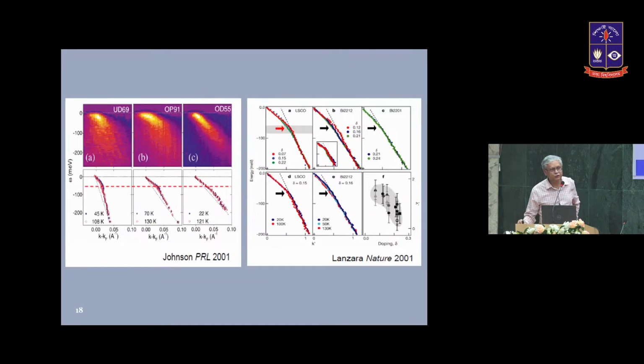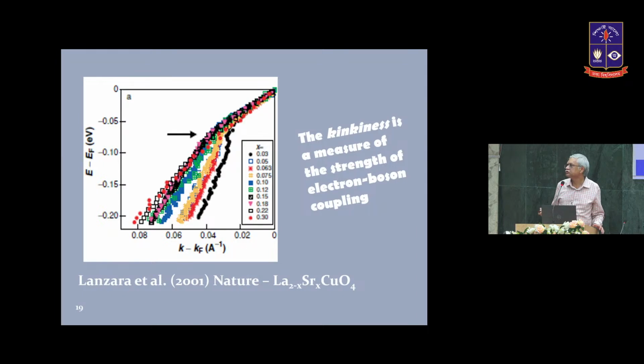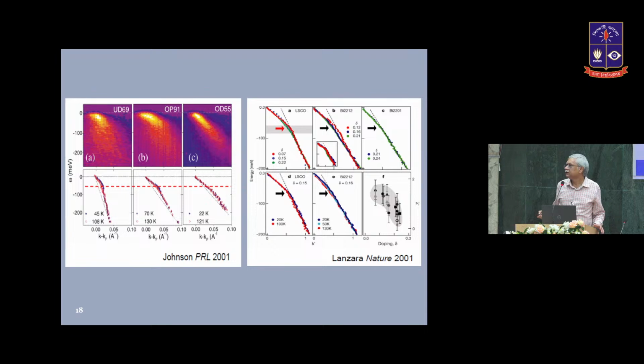And from this dispersion, it is also possible to calculate the electron boson coupling constant. So very roughly, if the kink is very strong, the coupling is also very strong. So that happens in copper oxide superconductors. And here, from the ARPES, if you do a very careful analysis, you can find out the electron boson coupling constant, and it has a doping dependence. You should remember the electronic phase diagram. It starts like this, then it rises to the top, and then on the overdoped side, it goes down. So, on the underdoped side, this is less doping. The electron boson coupling constant is quite strong. And with increasing doping, the electron boson coupling constant is going down. And this has many factors which need to be explained, and I will try to touch on it. Okay.